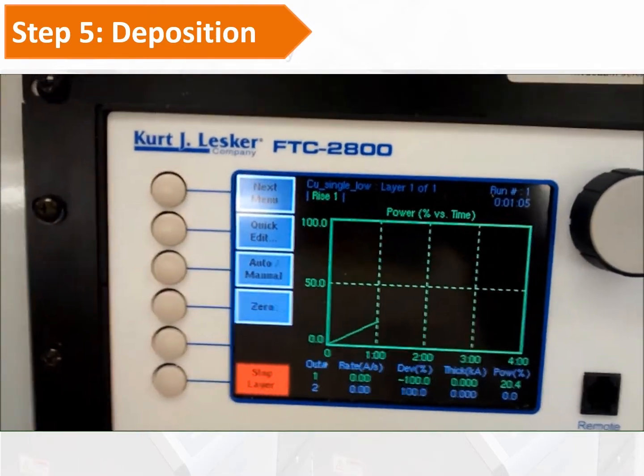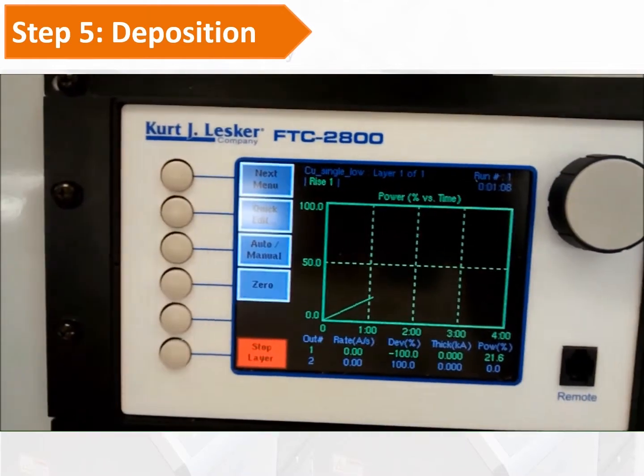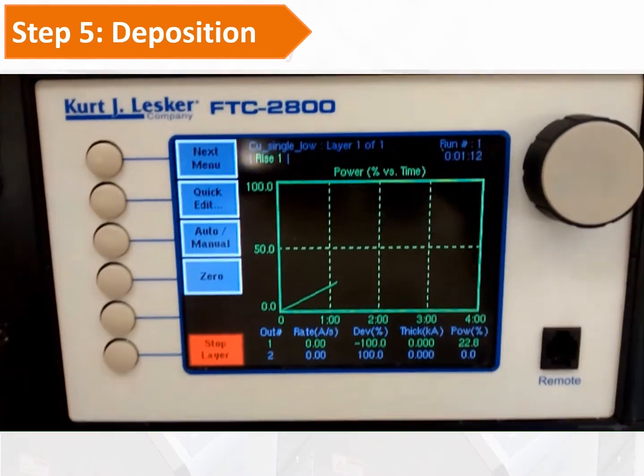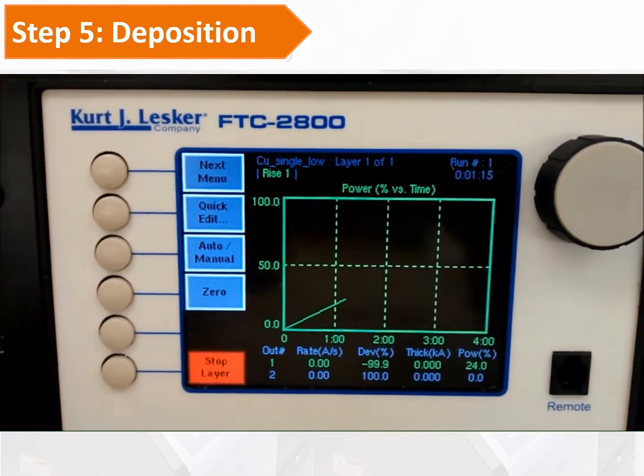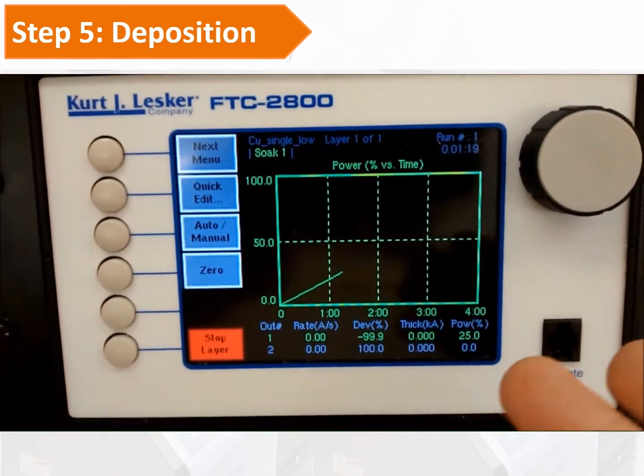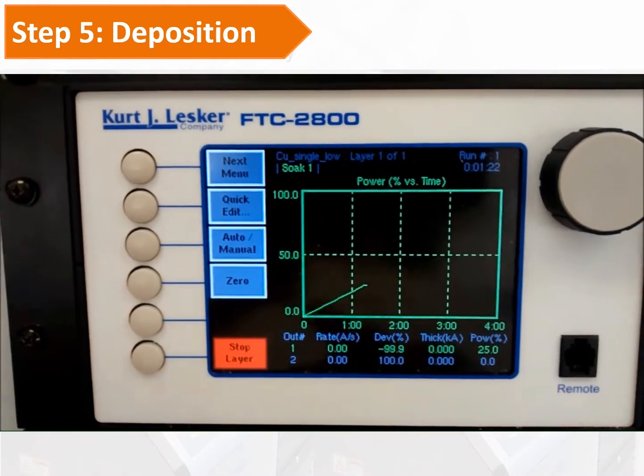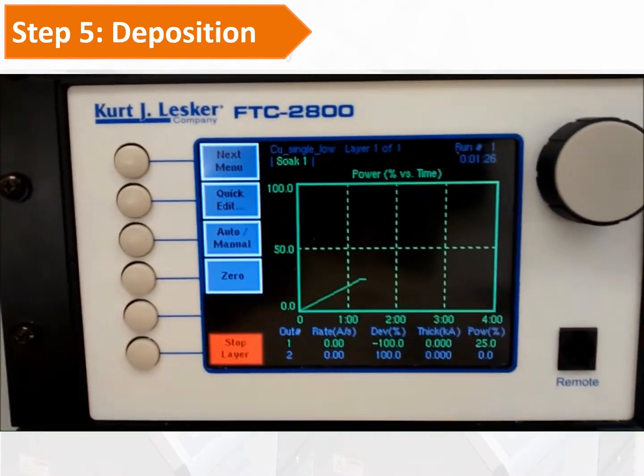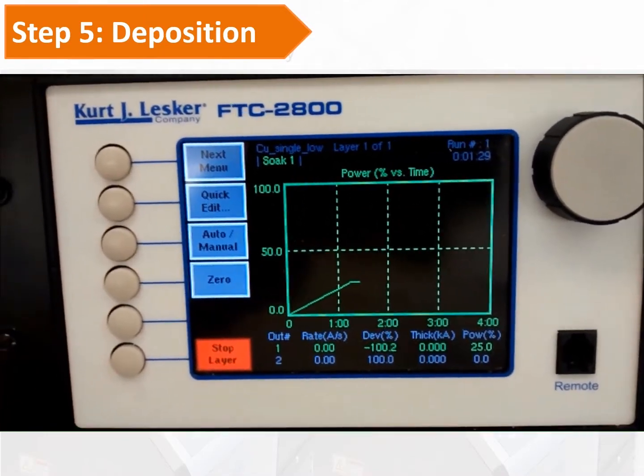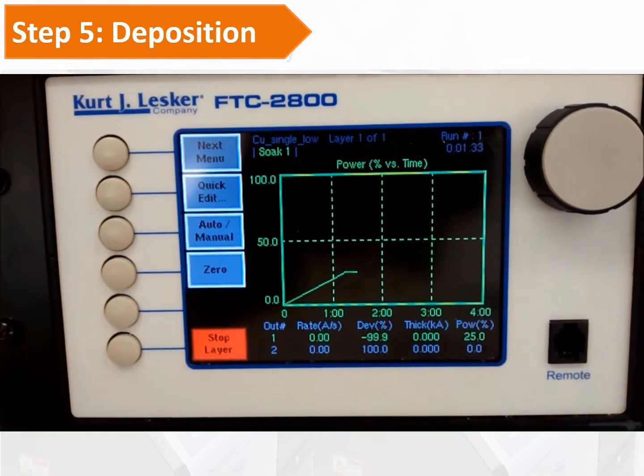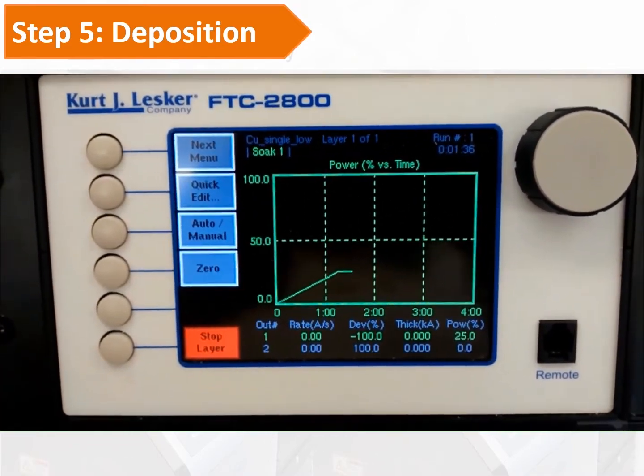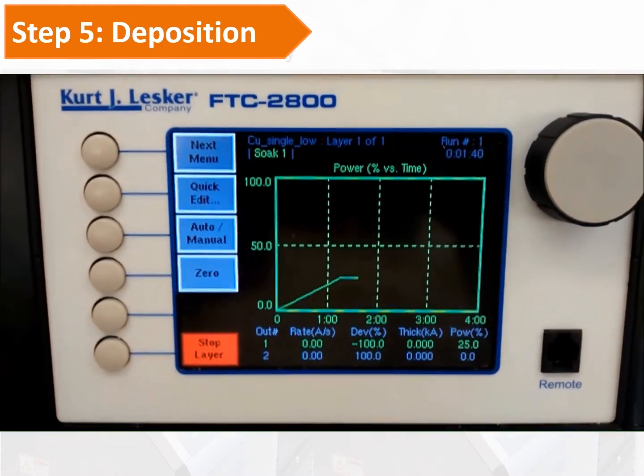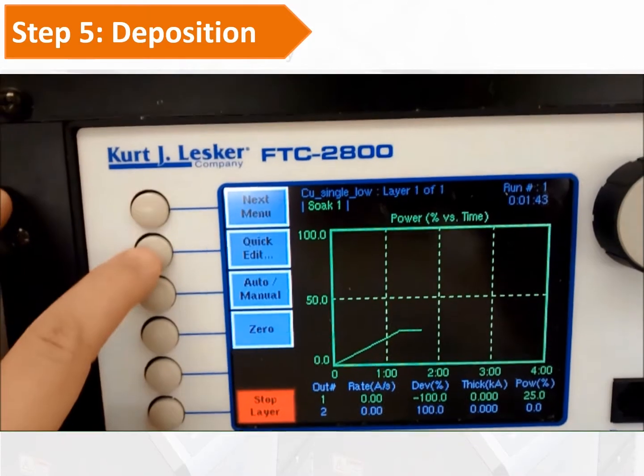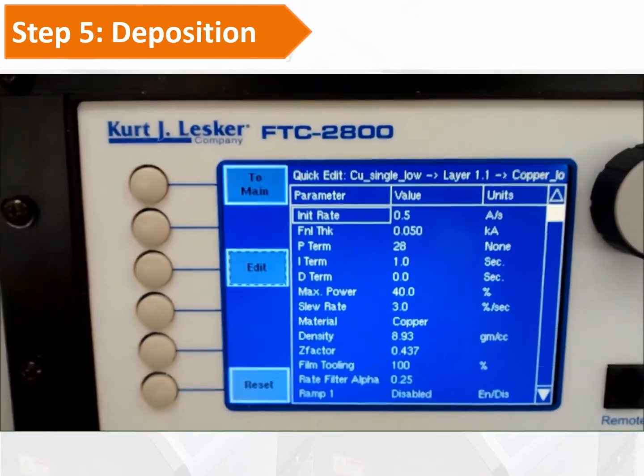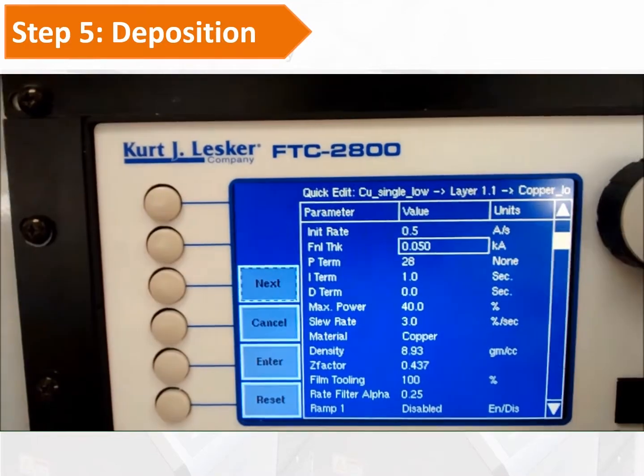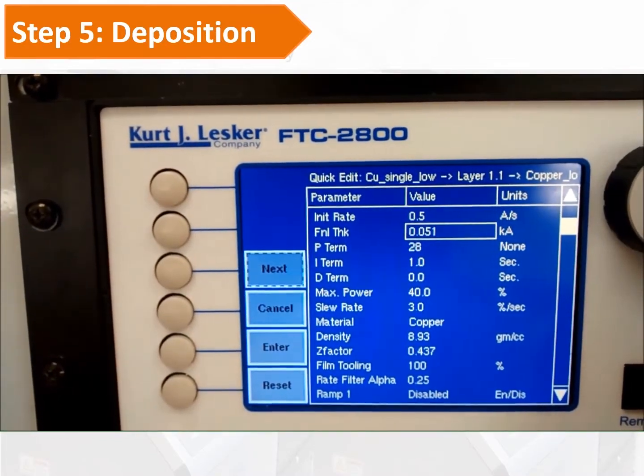During this time, we still keep the shutter closed. If there is some oxidation on your evaporation material boat, or some contamination in that boat, those oxides or contamination will be blocked by the shutter and cannot reach your sample surface. When the soak 2 phase is finished, the shutter will open automatically, and the material can go to your substrate and form the thin film on top of it. During deposition, if you want to change the deposition thickness, you can still change it through the quick edit. Before your deposition thickness reaches the set value, you can always change it.